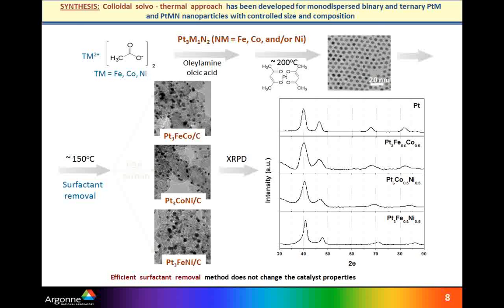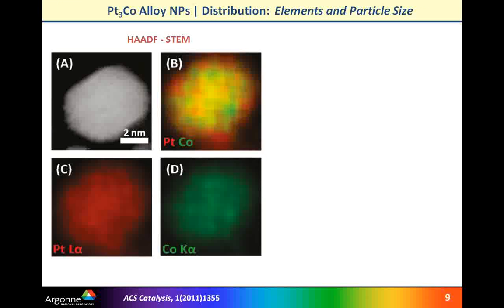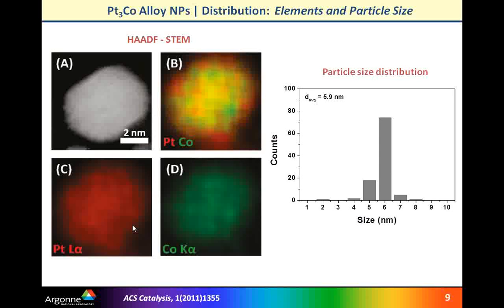And actually, the next slide shows one particular example, platinum-3 cobalt nanoparticles, and those are results from high-resolution TEM studies and also an effort to establish the exact elemental distribution. And one can see that the different elements, platinum and cobalt, are homogeneously distributed throughout the volume of one single particle. But what is even more important is the very narrow particle size distribution, and this is a unique advantage of